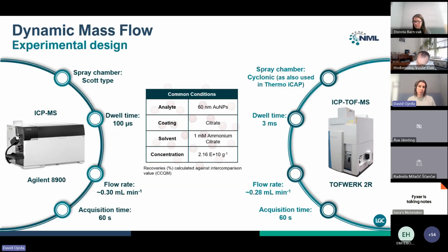Then in this slide, we specify the experimental design for this expansion of the boundaries. On one hand, we have one instrumental setup, which is the Agilent 8900 triple quad, with the Scott type spray chamber and using dwell times in the range of microseconds. On the other hand, we have ICP-MS from TOFWERK, in which the spray chamber is a cyclonic one that is also used in the Thermo iCAP. And the dwell times in this case are in the milliseconds.